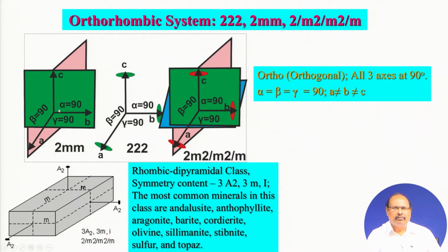2 is your vertical crystallographic axis. So, this is the direction, that is your vertical two-fold axis of symmetry, which coincides with the C crystallographic axis here. And you have two vertical mirror planes, one of this orientation here, another mirror plane of this orientation here. If you take a direction orthogonal to this mirror plane, this will be your A crystallographic axis, whereas in this mirror plane will lie the B crystallographic axis and C crystallographic axis.